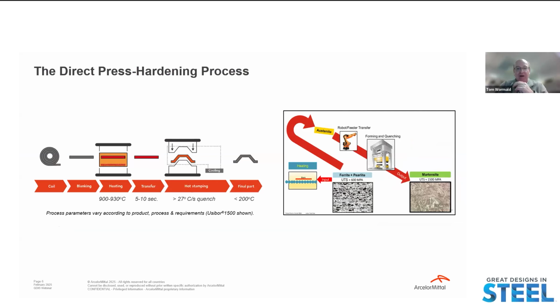The direct press hardening process involves heating the blank up to 930 degrees Celsius and performing the forming and quenching process virtually simultaneously in a water-cooled die.